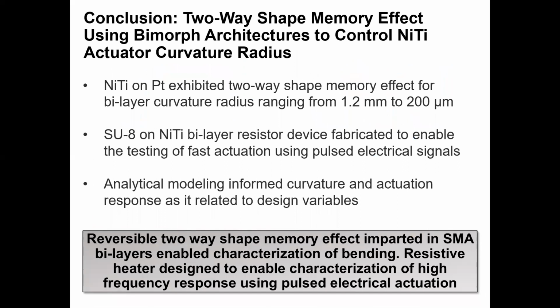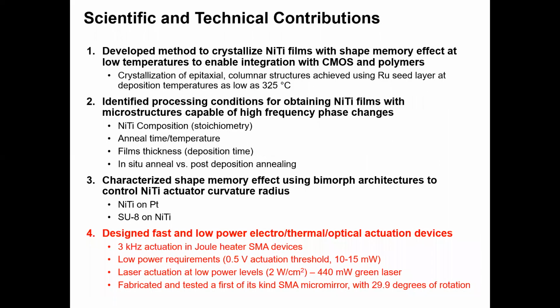The conclusions from this section of work were based on a comprehensive study of the two-way shape memory effects for 2 different bilayer configurations, one of which was NiTi on platinum, and the other was SU8 on NiTi. In each case, an understanding of the deflection and curvature was validated with complementary experimental and analytical modeling. Curvature radius was shown to be tunable over a range of millimeter to micrometer scales, and reversible deflections due to the shape memory effects were considerable. These ultra-thin bilayer MEMS actuators were engineered to actuate quickly and at lower power levels using either laser irradiation or pulsed electrical currents to induce the phase change. And the fast actuation is the subject of my final main contribution.